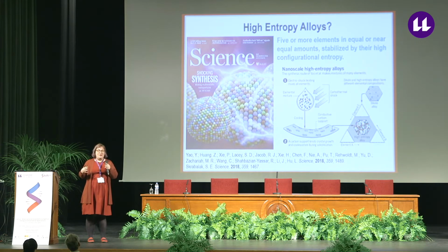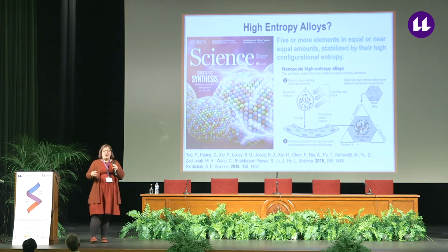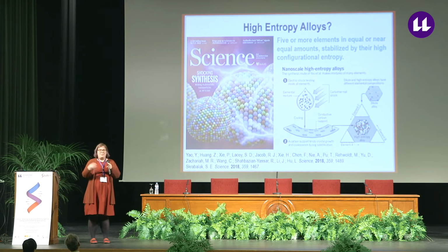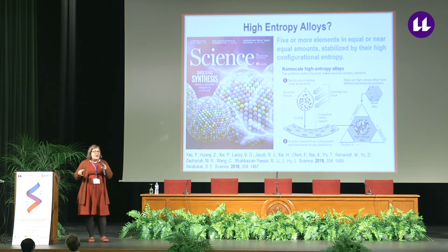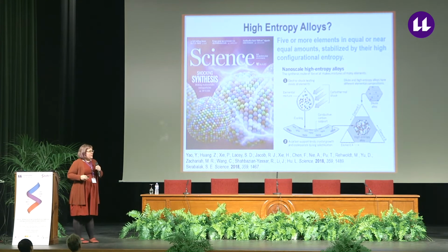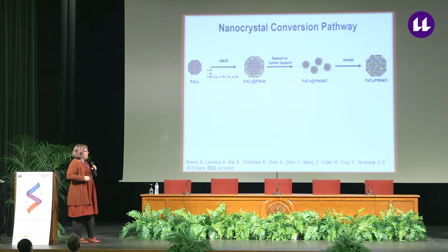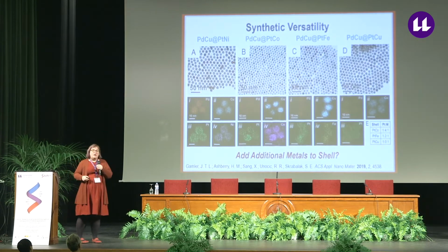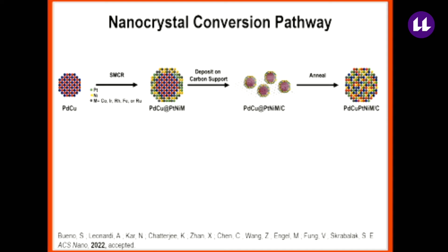They took 5 different metal precursors and tried to reduce them simultaneously in a traditional solvent system. And anybody who's done nanoparticle synthesis probably already knows the outcome. You get garbage. You get a mixture of different nanoparticle shapes and compositions, and it's just an utter mess. And so we took a step back and started to think about our original system here. We're already very close in that we have 4 metals in a single nanoparticle. We just need to get to 5 and get them to mix. So we took our seed-mediated co-reduction approach, and instead of doing 2 metals in the shell, we did 3. And it works well because the deposition is favored on that seed surface.